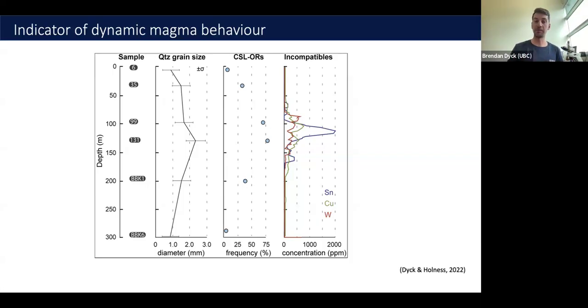So this is a really nice example of using microstructure to understand the crystallization history of, in this case, a high silica granite. So we must have had random grain interactions, quartz crystallizing, and the center of this body had more time both for the quartz grains to grow, but also had more opportunity for interaction to occur. So one way of interpreting that is perhaps you had dynamic motion, you had convection during crystallization, and it was centripetal crystallization from the margins inward, which would explain this elevation of these mineral incompatible elements like tin.